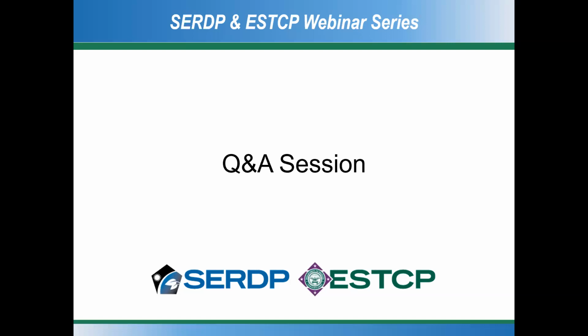Yes, we did evaluate fatigue for these, and the testing wasn't done before the slides were drafted, so it didn't make it into the slides, but I can summarize the results. The testing we did was 4340 substrates with WIP C1 and WIP C2 coatings, and also a baseline of chrome plating coating. We didn't test W1 or W2 because we ran out of time and resources. But what we found is that there was very little difference in the fatigue life of our samples when comparing the C1, C2, and chrome plating.